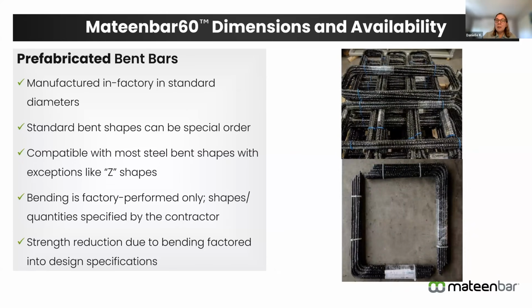We do offer prefabricated bends. As I'm sure you're aware, the GFRP cannot be bent in the field. It must be formed within the manufacturing facility while the resin is uncured. But really, any of the standard bend shapes that you would be used to ordering, you can see some stirrup type shapes here. We can certainly have circular hoops and spirals, and that would just be considered within the order. Obviously, in this particular case, we're really serving as the manufacturer and the fabricator for the GFRP bars.